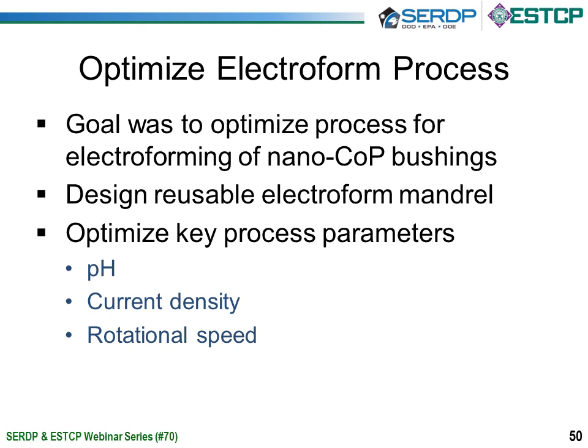So the next slide. The goal was really to specifically optimize the electroform process for this material, with the intent of electroforming bushings. Another goal was to come up with a reusable mandrel design. The initial ones were just stainless steel rods. They were disposable. They were machined out of the electroform. Obviously, this is not a cost-effective process, and from a waste perspective, really not desirable. So that was also one of the tasks. The three key process parameters that were identified were pH, current density, and rotational speed. And so I'll go over these individually.